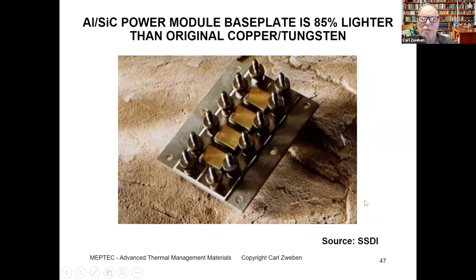of about 85%. Now, my primary background is in structural composites. It's very, very rare. As a matter of fact, I can't think of a particular application where we demonstrated a weight saving of 85% compared to the baseline material. But with a direct substitution of one material for another in electronic packaging, we can see these very high weight savings.